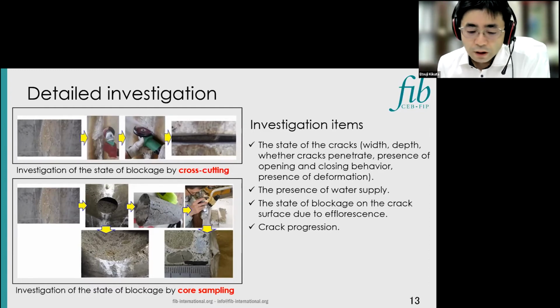Detailed investigation was conducted for 2 years in order to confirm the progress of cracks. The photo shows investigation of the state of blockage on the crack surface. The photo below shows a general investigation method by core sampling. The photo above shows a method called cross-cutting, in which a cut is made at a right angle to the crack using an electric tool. By the way, using this cross-cutting method makes it possible to create injection ports and inject materials even into cracks that have surface blockage.